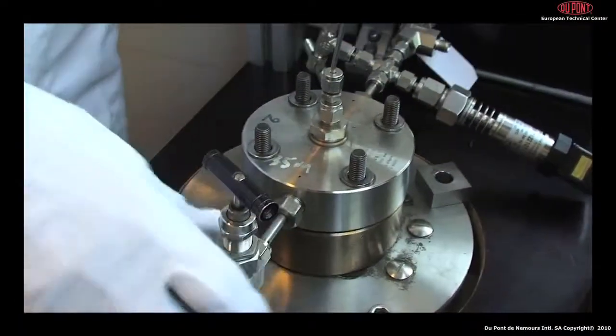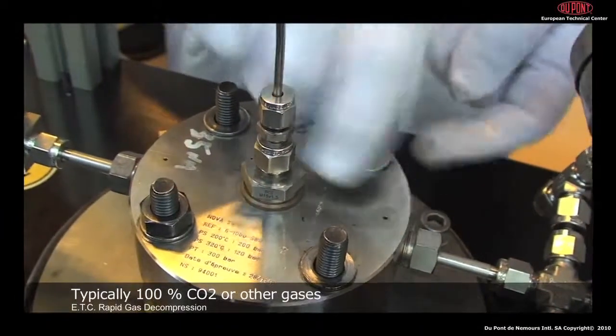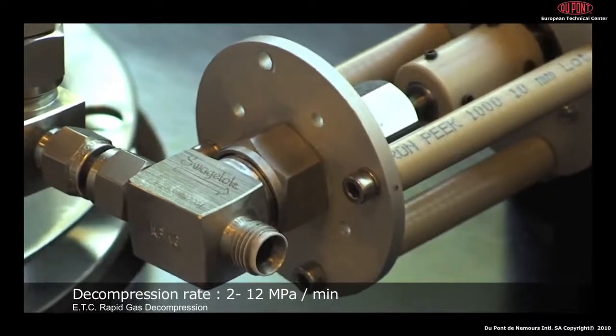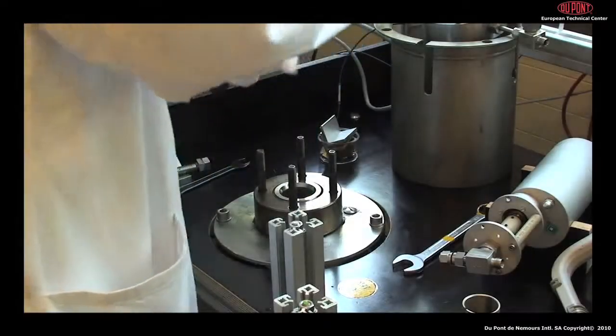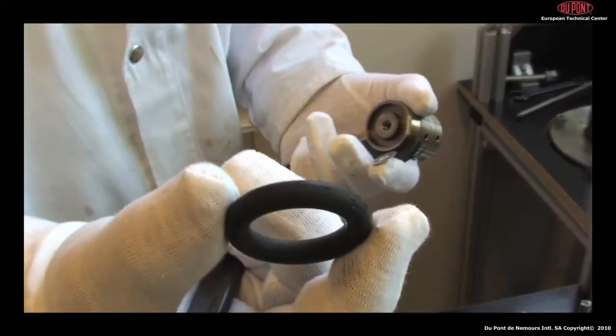After typical exposure to these conditions for 24 hours, the autoclaves are decompressed at a well controlled rate. The autoclave is opened and after another 24 hours conditioning, the O-rings are released from the jigs for inspection under a microscope and rated according to the NORSOK M710 standard.